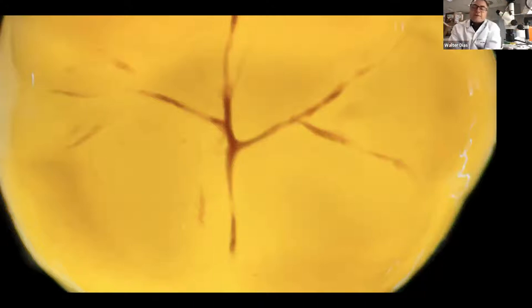In order to accomplish this, of course, I told you, you should always seal the dentin whenever you have the space, especially for posterior overlays and onlays and even crowns. You can seal this very easily. For anterior, sometimes we don't have enough space and maybe you can seal it only with the adhesive and then a bond. But especially for the posterior or large cavities, you can seal it.